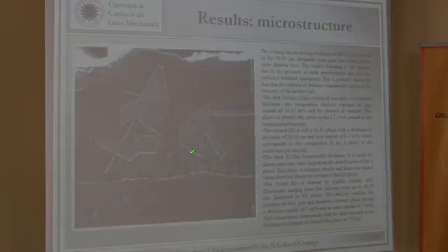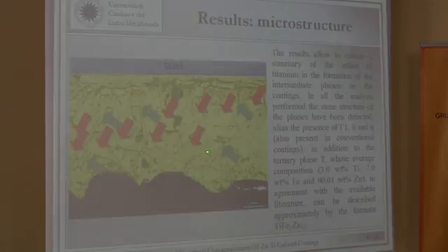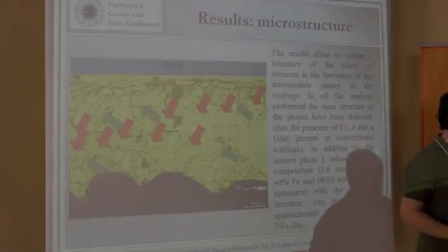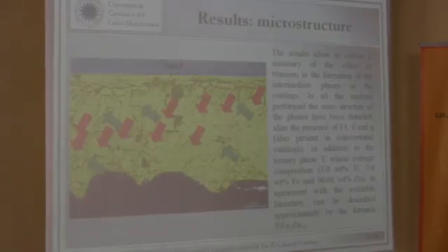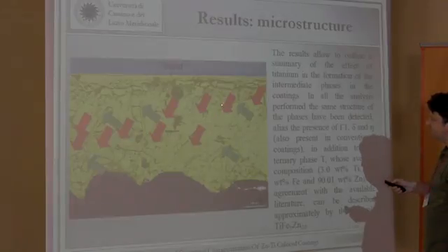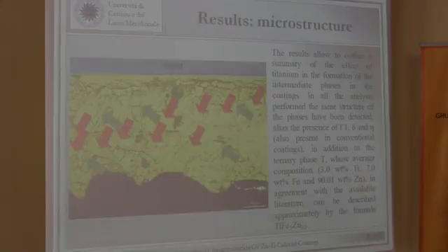We have named this phase as tau phase. The XRD diagram, diffractogram, presents different peaks. You can see the peaks indicated by a black dot. Analysis of this spectrum shows the presence of a phase much richer in titanium and iron. Other analysis of morphological position shows the position of this phase along the longitudinal direction parallel to the surface. We show the formation of this phase from the delta phase, and then we have a moving of this phase toward the external phase.